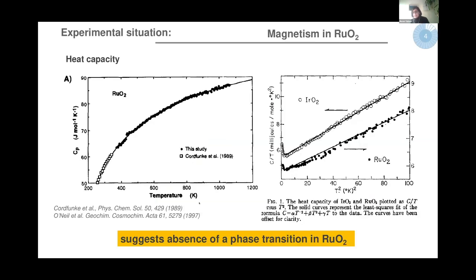So now if we go back in history, this material is known from a long way back. There are reports from the 30s talking about this material. And what I'm showing here first are thermodynamic measurements that were done already in the 80s and even before that. If we look at heat capacity, for instance, what we observe is that in all this range of temperatures, there is no phase transition manifestly happening. So there is no discontinuity in the specific heat.